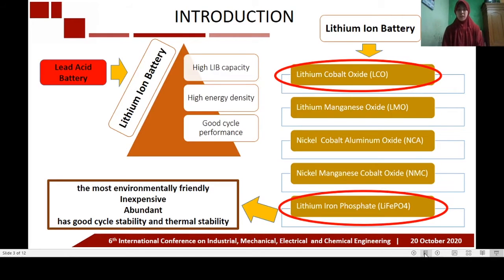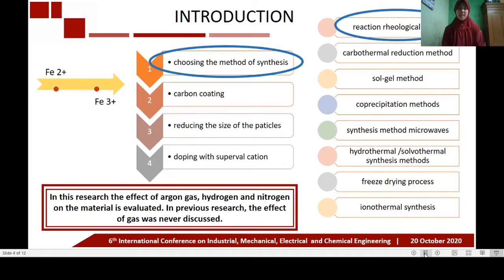Lithium iron phosphate is considered the most environmentally friendly, inexpensive, abundant, has good cycle stability and thermal stability. However, lithium iron phosphate is easily oxidized in water and air. Long exposure to air causes oxidation of ferrous to ferric, which can limit electrochemical ability and reduce battery performance.